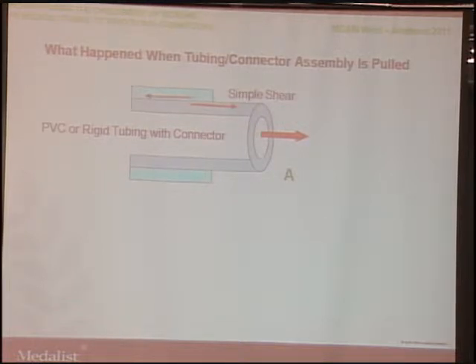So, even though it has a similar Poisson ratio, when you stretch it, the diameter does not reduce much. Here shows the tubing and the connector diagram. When the tubing is very rigid or made of PVC, when you pull it, the diameter does not change. So this simple shear gives you a pretty good retention force. And in fact, the force along the interface between the connector and the tubing is pretty uniformly distributed. So you can get a really high retention force.